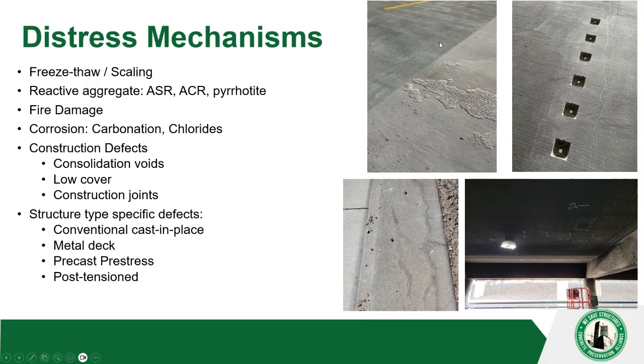This is a scaling photo. You see here, there's no issue because that's where they stopped the coating. Here they have an issue right next to it. It's kind of a problem there. This right here, you have a metal pan deck with shear studs that are too close to the surface. And then you see this crack, which is running parallel to the beam, just because the beam is stiffer than the metal pans. And so that crack allows water to get into the pan. And then if this is downhill, it will flow in and corrode everything down below it.